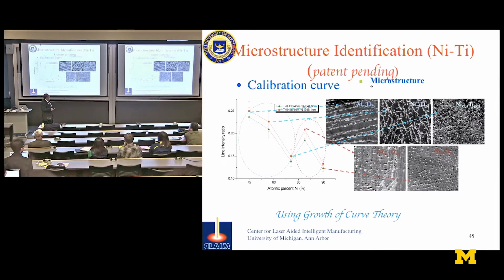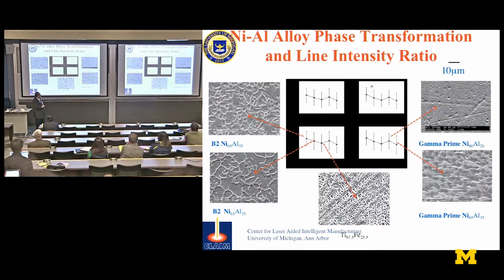So by looking at the plasma, and this calculation doesn't take more than a few milliseconds, I can immediately tell you at what percentage my composition will change and what kind of structure we can get. And we tried multiple systems. This is for nickel titanium. This is for nickel aluminum. And nickel aluminum is very important because that's the base of nickel superalloys. You'll see a kitchen sink in the nickel superalloy, but essentially it's a nickel aluminum structure. You're replacing one or two aluminum atoms with some other element. So even with all kinds of different alloys, we tried this and we found that the slope always changes, associated with the phase change.